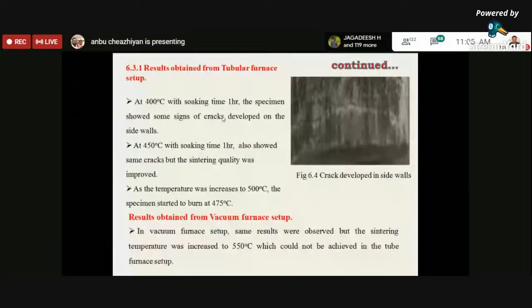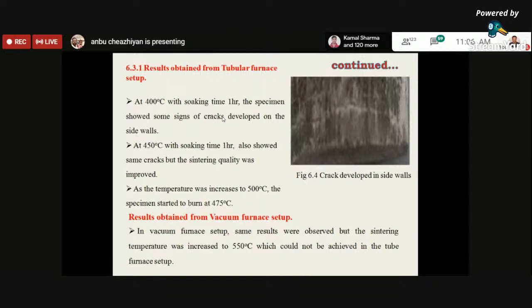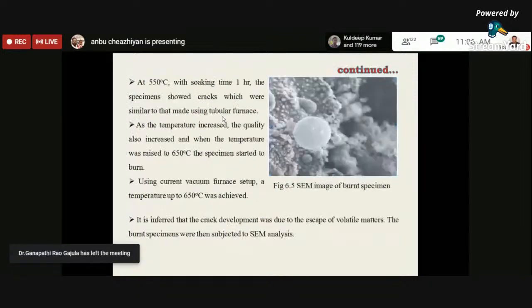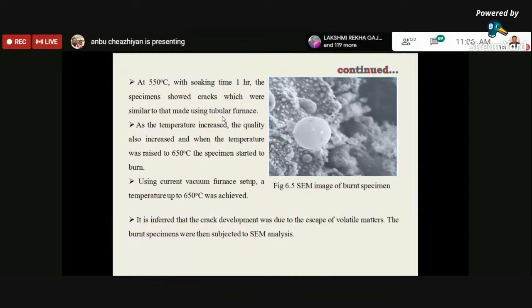So we tried to increase the temperature, and we went for another setup, the vacuum furnace setup. In that, we first increased the temperature from 400 to 500. In the vacuum furnace setup, the same results were observed, but the sintering temperature was increased to 550 degrees centigrade, which could not be achieved in the tubular furnace. At the same time, only the sintering quality has been improved. Again, we went for 550 degrees centigrade with a soaking time of 1 hour. The specimen showed cracks which were similar to those made using the tubular furnace.